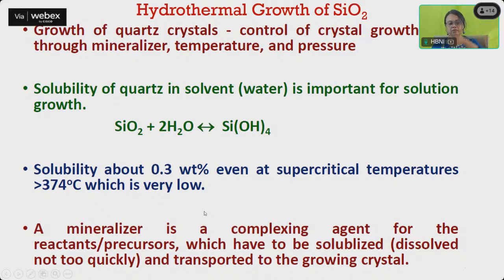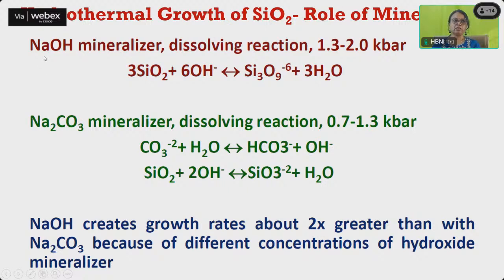So we are adding some agent. This is called the mineralizer. It's a complexing agent for increasing the solubility. Generally NaOH or Na2CO3. These are the two general mineralizers used for the growth of silicon oxide, SiO2 or quartz. With NaOH, it makes it easier for SiO2 to dissolve in water, and then it gets crystallized.